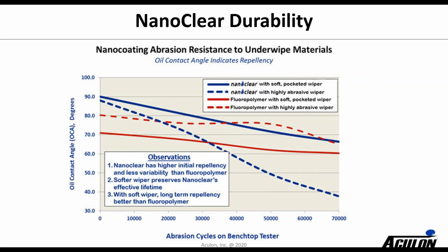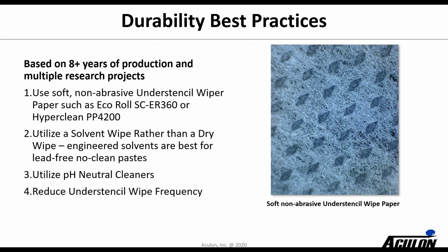Here we have some data on the durability of NanoClear. We have information on some best practices for ensuring a long NanoClear coating. So we do recommend that the right cleaners are used and that a soft pocketed wiper is utilized with NanoClear. And as you can see from this data, if a soft pocketed wiper is utilized with NanoClear, it will outperform the competitive technologies for up to 70,000 prints. So we do recommend utilizing a soft pocketed wiper and non-caustic cleaners, and you can be assured that the NanoClear is going to last for an extremely long time.